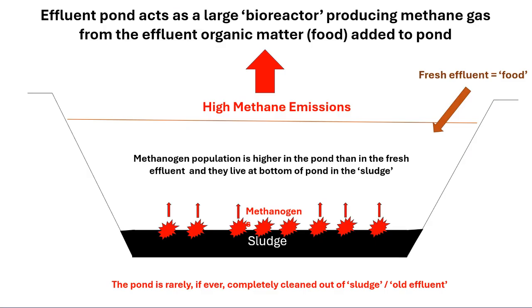So essentially, the dairy pond is what we call a large bioreactor. Every day, the farmer, after milking, cleans the yard and cleans the parlor. All that dirty water is washed into the pond and carries with it the organic material, which usually settles at the lower part of the pond. And that's where a lot of the methanogens, the methane-producing microbes, which are usually archaea, love the organic carbon. So we are feeding the methane-producing microbes every day with fresh carbon, and they're producing methane constantly. If you observe the pond long enough, you'll see some bubbles coming up.